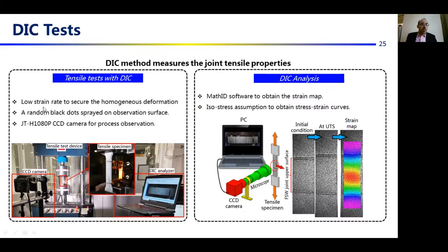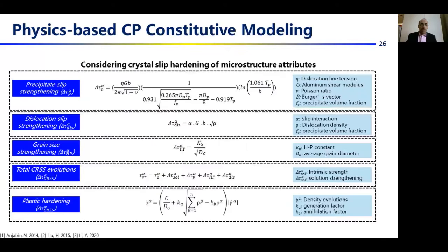And the DIC method measures the joint local and global tensile properties. They include a low strain rate to secure homogeneous deformation throughout the joint. Random black dots are spread on the observation surface for the camera to observe the material deformation, and a CCD camera for the process observation. For DIC analysis, the MatchID software obtains the strain maps from the initial condition in the tensile test of the joints to the UTS, and an iso-stress assumption is also used to obtain the stress-strain curves from the DIC results.